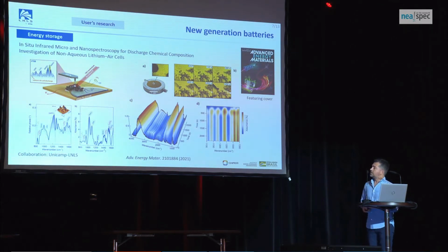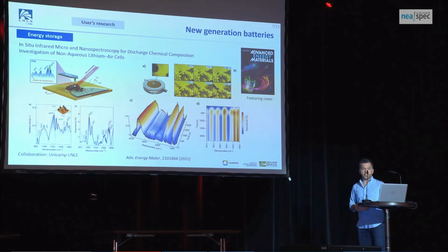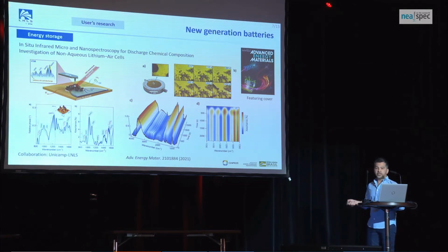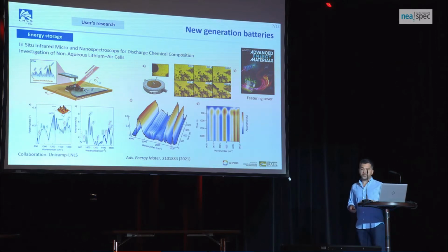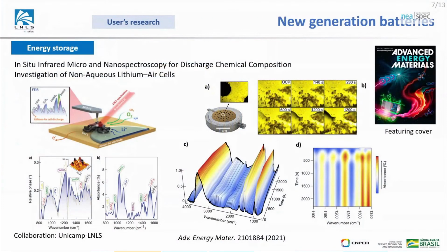So here, these collaborators were studying new generation batteries, more exactly metal-air systems. We know that these systems are key for large-scale energy storage, as they hold the highest energy density for any electrochemical device. So here what they did is they combined micro-FTIR and nano-FTIR to study those systems in an open-air cell. And first, they have here an operando experiment where they monitored the discharge of the system with the FTIR, so they could see that actually the spectra don't change that much with time, which is a good sign that chemically there is not much change in the cell.